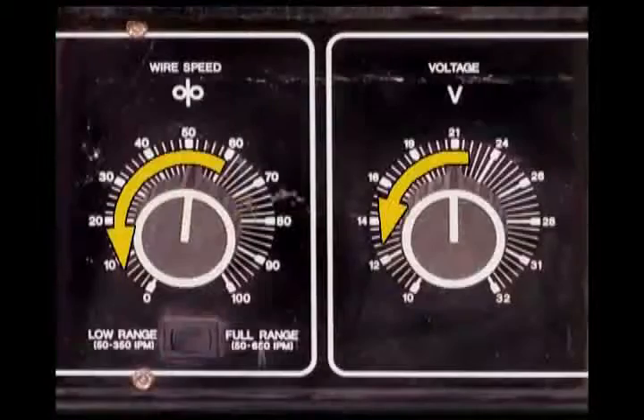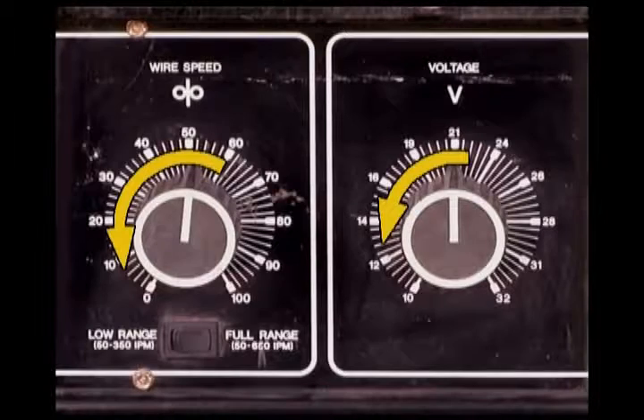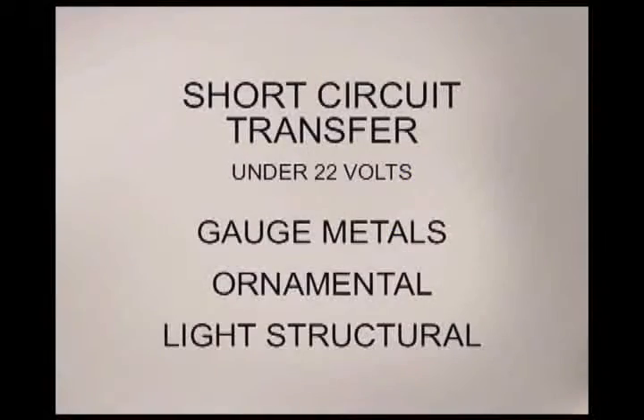This arc on, arc off allows the molten metal to cool enough so that welds can be made in all positions: flat, horizontal, vertical, and overhead. Short circuit transfer is considered to happen at settings up to 22 volts. This voltage range and metal transfer is used for welding on thin gauge metals, ornamental type projects, and light structural.